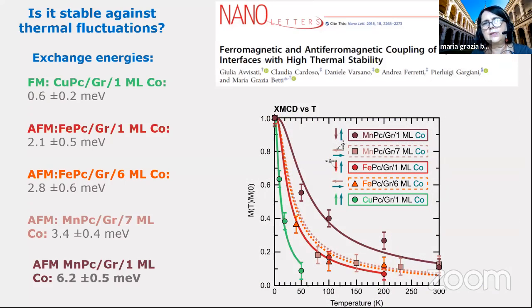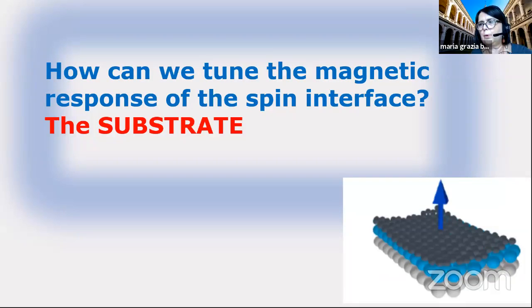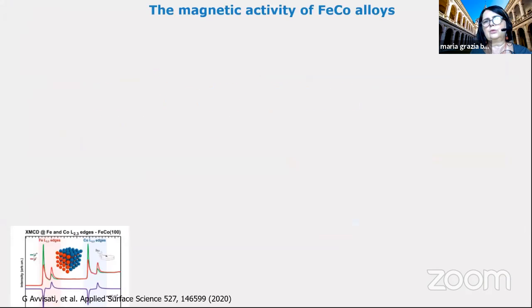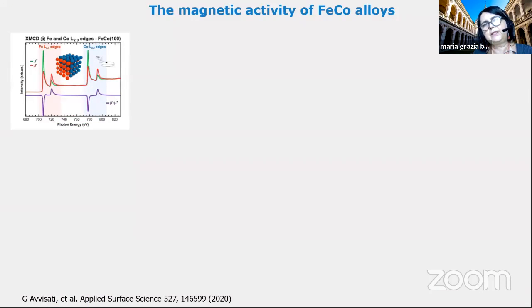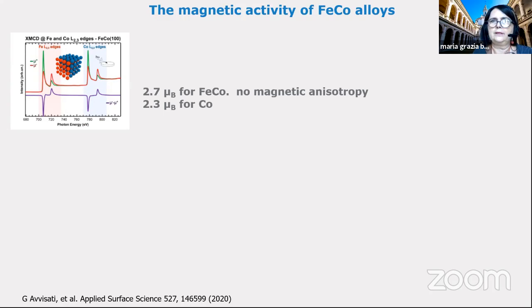So this is a good result, because we can say that we really have a ferromagnetic response at room temperature. Now I will propose to you a way to tune this magnetic state, not only by changing the molecule, but maybe by changing the substrate. We try to find another substrate, a substrate with a higher magnetic moment. So we know the highest magnetic moment among three-dimensional alloys is that of the iron cobalt alloy, where the magnetic moment increases from 2.3 for cobalt to 2.7.